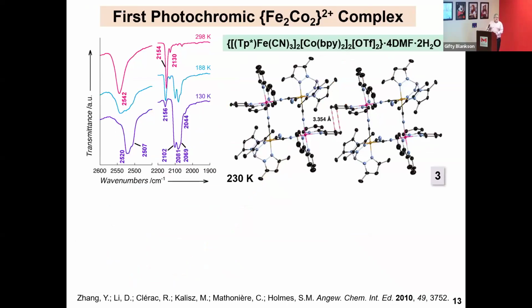It's the structure. Right? And that had been underappreciated for a number of years. So our first foray into this was making a molecular square with the same bits, Tp* on iron, bpy on cobalt, triflate. But now instead of 4 water molecules in the lattice, we inserted DMF to introduce disorder. That disorder is important for this breathing of the complex. In the absence of breathing, if you have a rigid environment around a cluster, it basically has congestive heart failure. It's not going to expand and contract. It's not going to do the electron transfer.